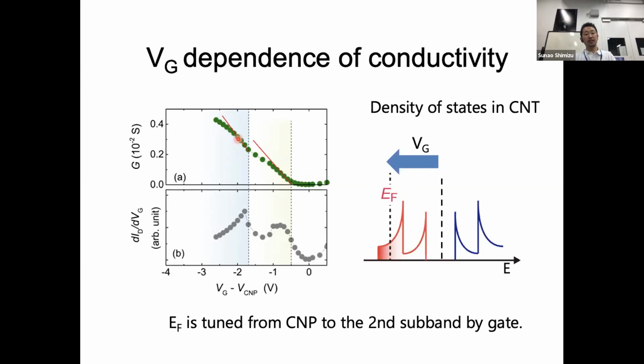In order to see it more clearly, we took the derivative and we also observed two peaks here and here. Those peaks correspond to the subband edges in the carbon nanotube thin film. The right figure shows the schematic picture of the density of states in the carbon nanotube. When we decrease the gate voltage, the Fermi energy shifts from the charge neutral point to the lower energy region. And when the Fermi energy passes the edge of a subband, we observe the change of the conductivity here and here.